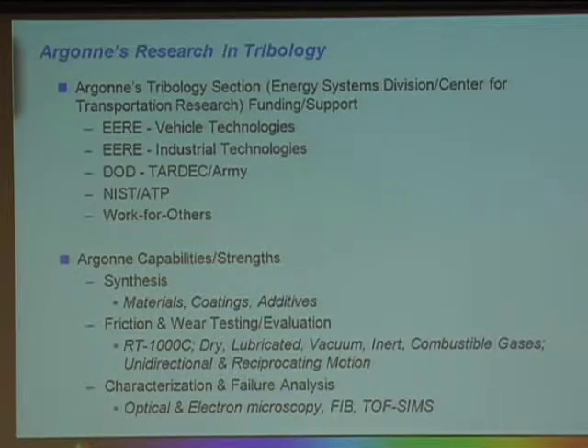We also use a wide range of loads so we can control the actual stress that's applied, because that does influence the phenomena of the failure mode. Then after we do the friction and wear tests and the synthesis, we utilize a number of characterization and failure analysis techniques. Many of them focus on optical and electron microscopy. We're starting to use some ion beam techniques that are really showing some promise, which I'll describe.